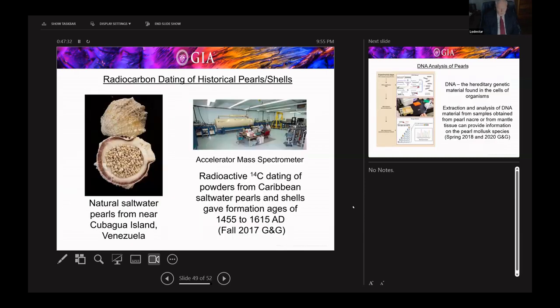We've also been doing a little radiocarbon dating for organic materials, in this case, saltwater pearls and shells. These are from an island off the coast of Venezuela in the Caribbean, which was one of the main reasons to draw the explorers from Europe like Christopher Columbus to the Americas. They were looking for these pearls. And we can radioactive carbon-14 date powders from a pearl or a shell to get a formation age. And this is something we've reported on.